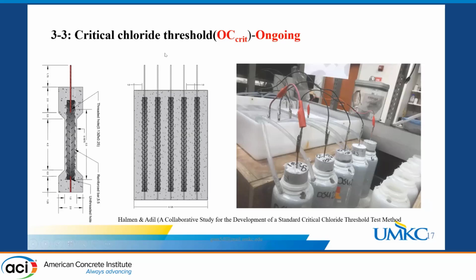This test method was originally designed by Dr. Trejo and Dr. Pavan at Oregon State University, but I have been working on it for the last 3 years, and in our round robin results, we showed that this test method is repeatable, which means we get the same result from the same laboratory, and reproducible, which means we get the same data from different laboratories. This test method comes with two parts: the anode part, which is dog bone shaped, and the cathode part. Usually, we cast 5 samples at the same time.